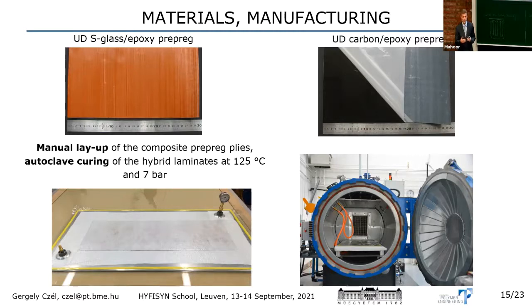and this, at least it is my opinion, that it's simpler than bonding or retrofit the end tabs even on the standard specimens. So sticking 10 plies instead of 5 together probably is easier than bonding the end tabs afterwards to the laminate. But of course you can argue with this. And yes, it is more material consumed because we have a full cover of glass epoxy on our specimens.